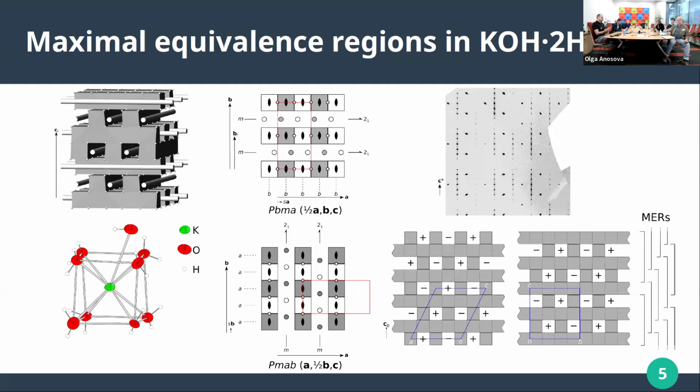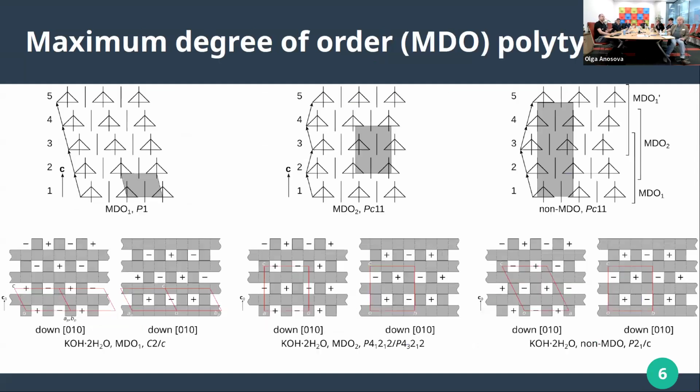Now, the whole idea is that basically all the structures are locally equivalent. So basically, if you ignore interatomic interactions beyond 1 layer, then you would say they're energetically equivalent. So you would expect that all these structures are completely disordered. But you cannot do that. It's always a bit of a simplification, and there are ordered polytypes.